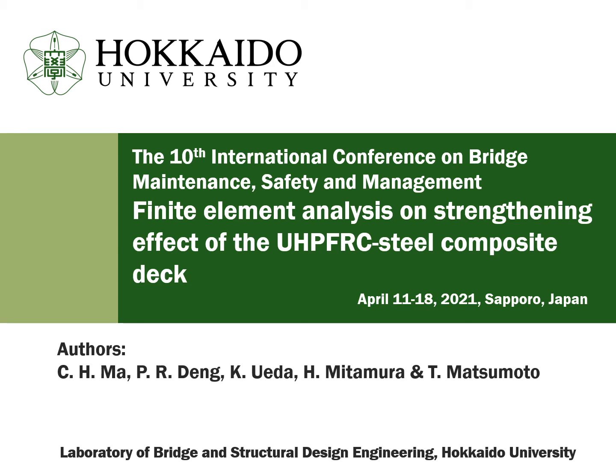In orthotropic steel deck, the transverse distribution of wheel loads generates high local stresses in the small thickness of the steel members. In order to reduce the stress level and thereby extend the fatigue life, a strengthening technique with the overlay of UHPFRC, ultra-high performance fiber reinforced concrete, was proposed and commonly used based on experimental studies. In this study, three-dimensional finite element analysis with nonlinear constitutive material models is performed to investigate the beneficial effects of the UHPFRC overlay in the composite deck.